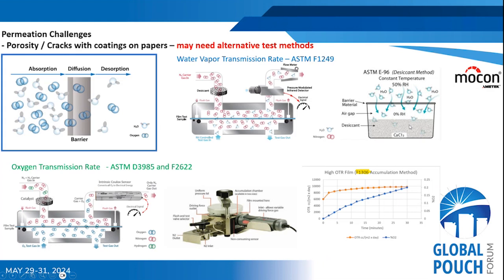And what we'll see is the weight changes over time, and it actually starts getting heavier. By plotting that weight change over time, I'll get a positive slope, and I use that to determine my water vapor transmission rate into the cup.